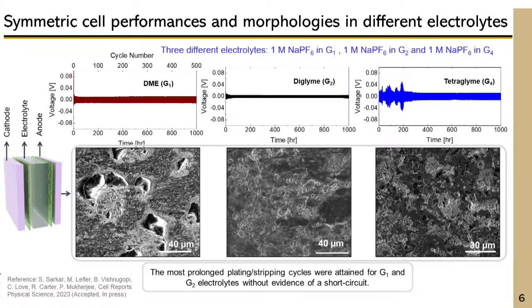Then after the cycling was done, we wanted to see what happened to the electrode that had gone through cycling. So we took it apart and took SEM images of this metal electrode, sodium metal, and you can see the metal surface has evolved differently under different electrolyte conditions. The last case showed, I don't know if it's visible from here, lots of small dendrites that had broken off and also a lot of corrosion in the metal electrode.